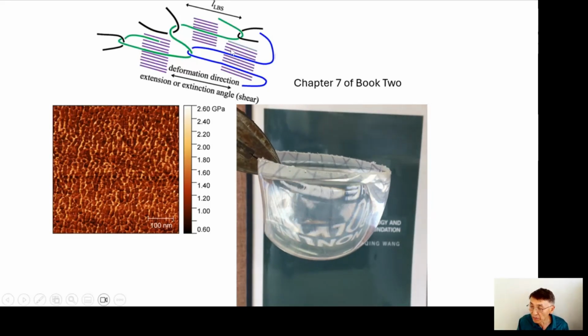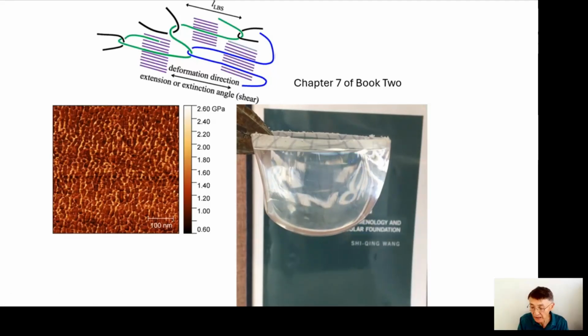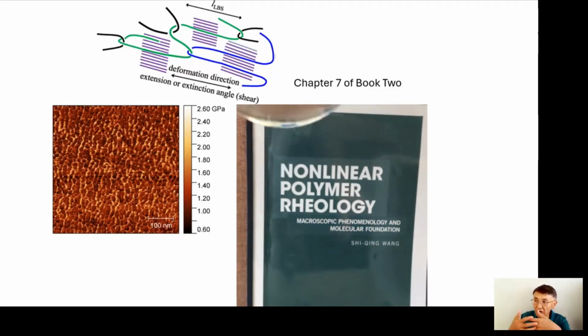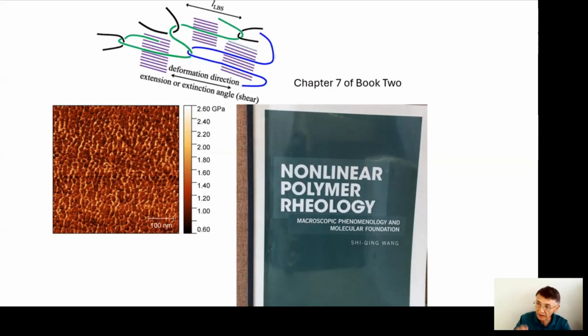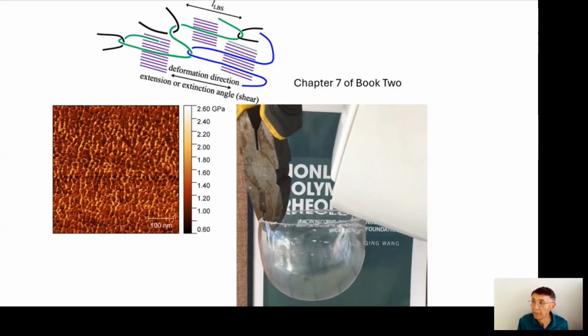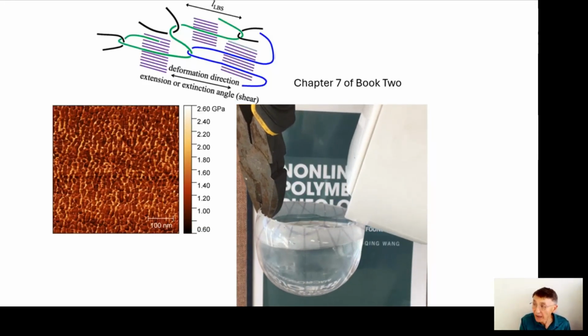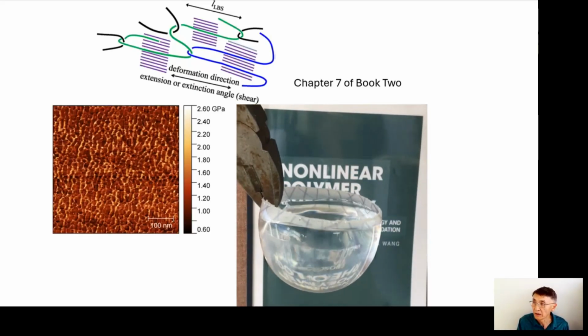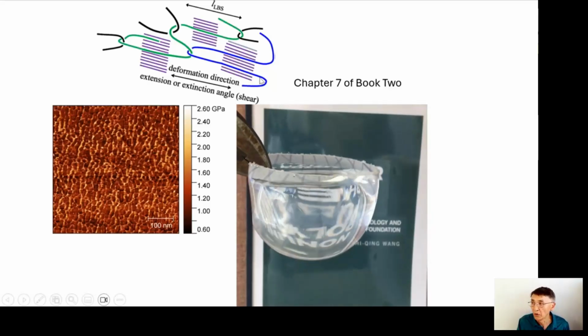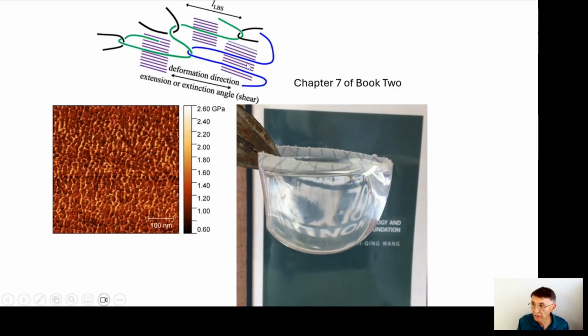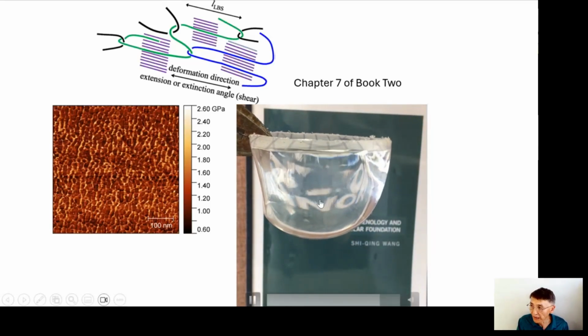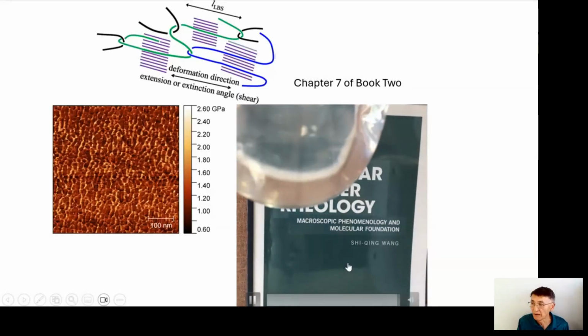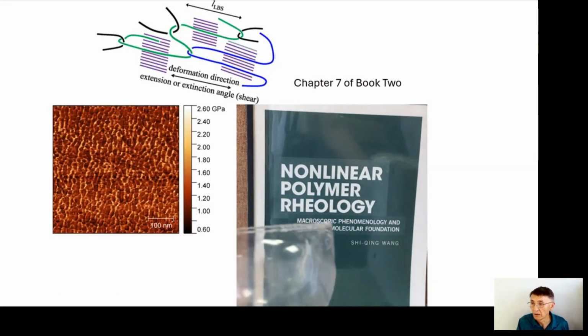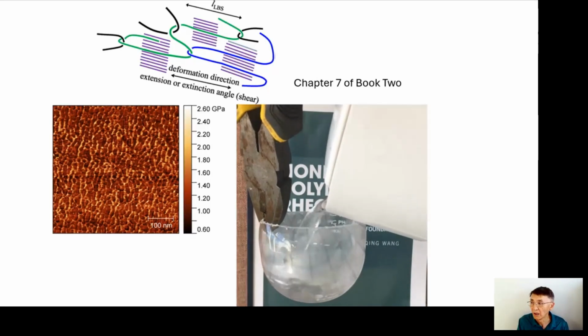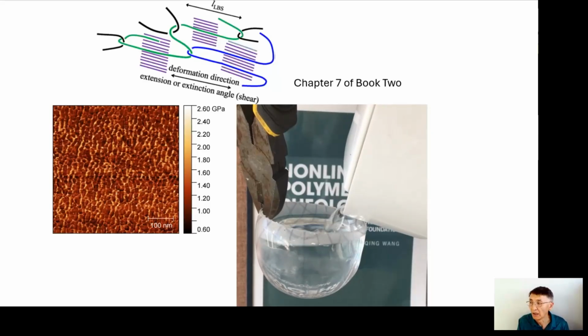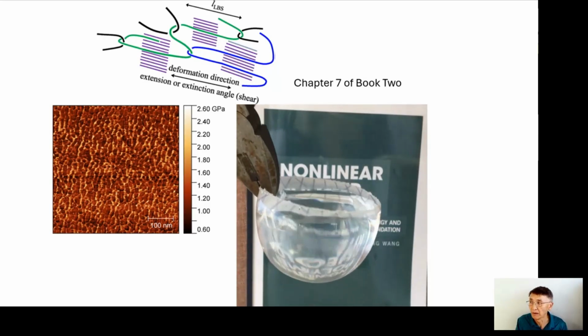We know the structure needs to be such that it can deliver ductility by intensifying the network strength in this XY direction at the sacrifice of the third direction, which is the film direction. We don't care. And then that is achieved through rheology. And once you have that, you can encourage the structure that involves crystallization. So you have the double benefit of achieving crystallization without sacrificing the transparency, and also achieving ductility. So this is really, I'm proud of this way of being guided by theoretical understanding to invent a material, if you like, or predict the property of the material in this case.